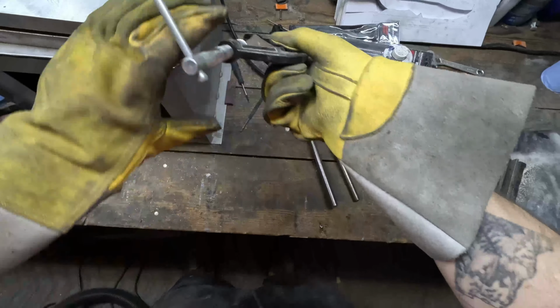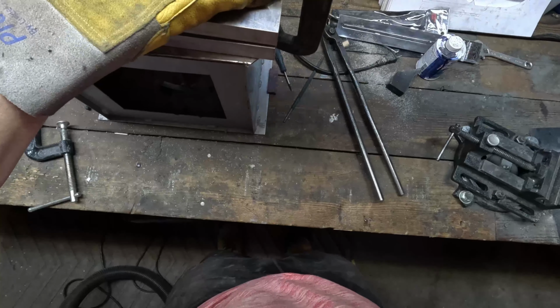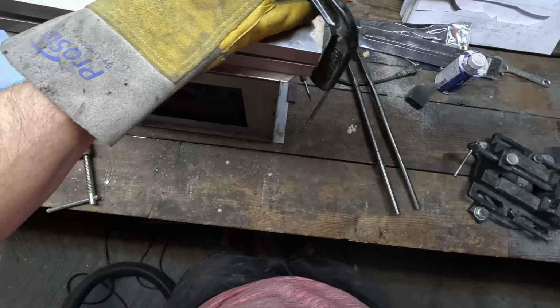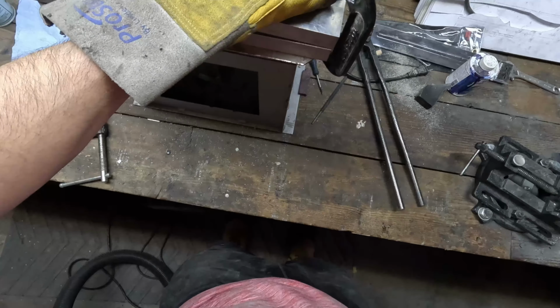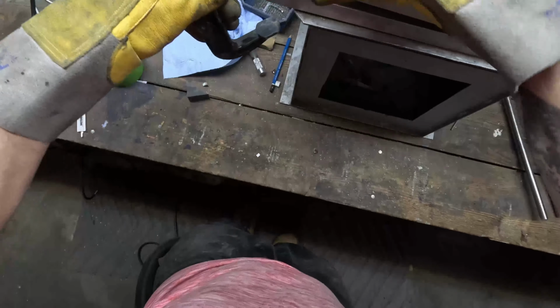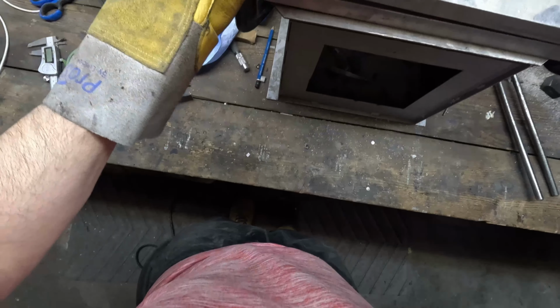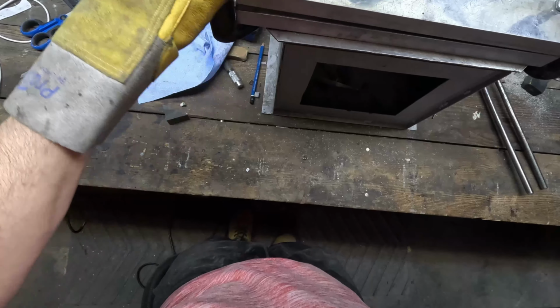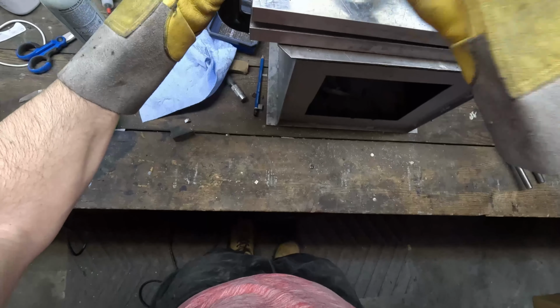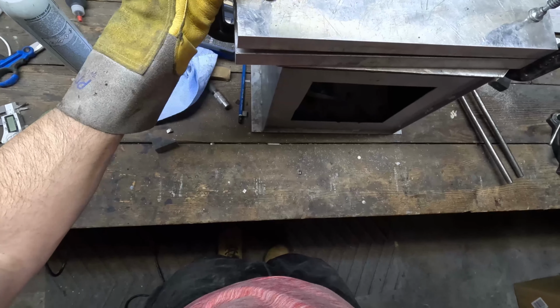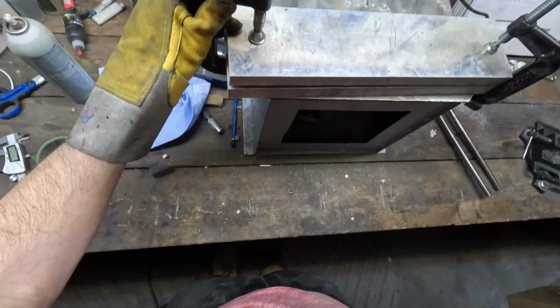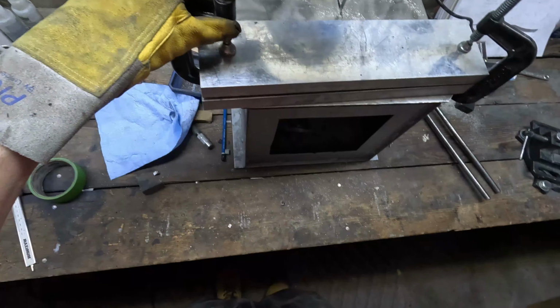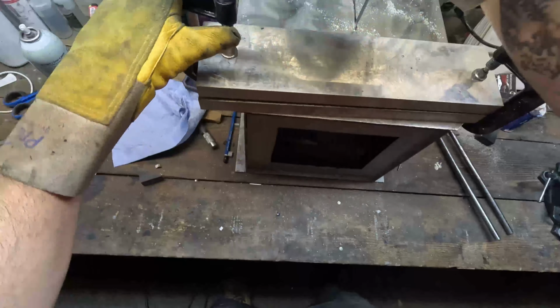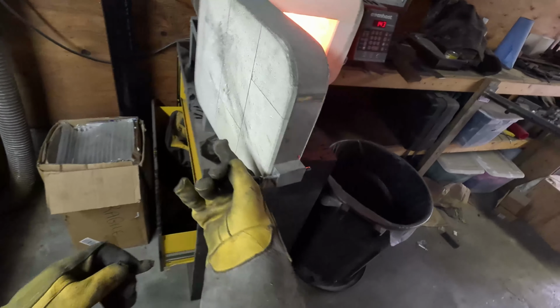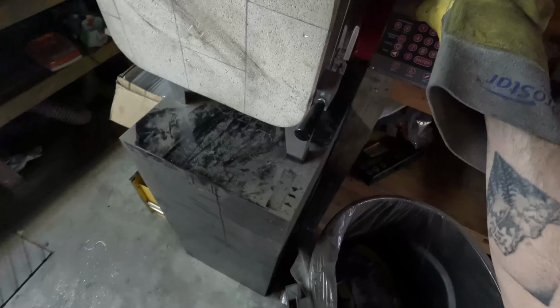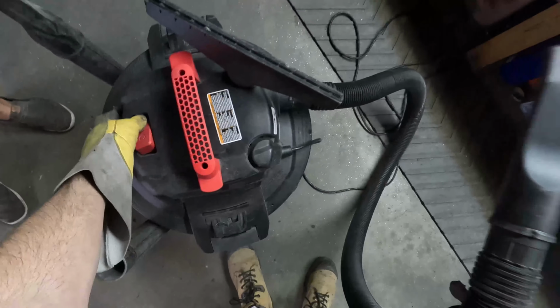Now for the actual heat treatment recipe that I use: I bring my kiln to 2100 degrees Fahrenheit, and we'll put the steel in there for 15 minutes, let it soak. What this does is dissolve all the carbon, vanadium, molybdenum elements that are in the steel. And once we shock them by bringing it from a hot temperature to room temperature in a small lapse of time, those elements will attach to the carbon elements and form carbides, which are super hard.